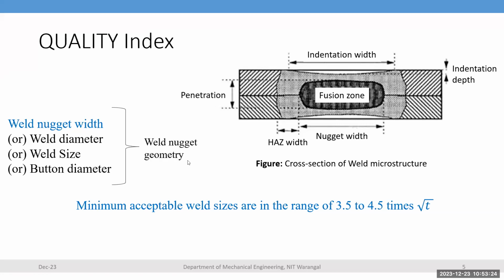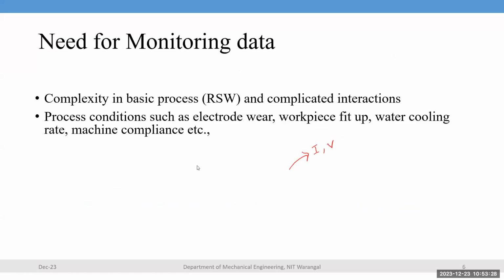So this is the weld nugget geometry. Then the need for monitoring data: the complexity in the basic process, that is resistance spot welding, and complicated interactions between the input parameters, material properties and input conditions of the process, so that we can have a lot of interaction among the variables. Then process conditions such as electrode wear, because you are doing multiple welds over a period of time. Due to that, heat is accumulated at the interface of the sheet and the work material. Anyhow, you are applying the pressure. Due to that, heat is accumulated over a period of time so that material degradation takes place. Then wear of the electrode takes place during the process.